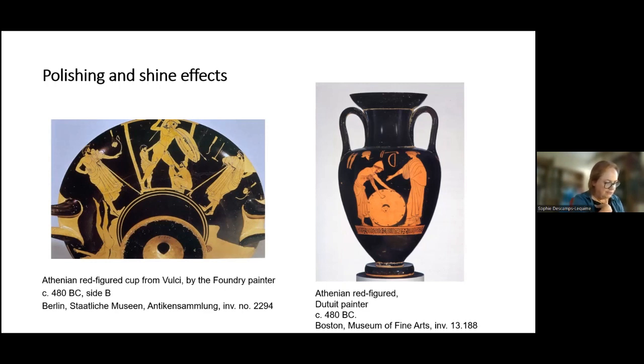Craftsmen completed the polishing process, as depicted on the foundry cup, by using a metal scraper. This tool, removing fine shavings, produced notches of varying depth, oriented according to the way it was guided. The scraper also vibrated to create small depressions perpendicular to the notches. These ripples were so dense that they generated significant light diffraction effects, accentuating the three-dimensionality of the works at locations chosen by the craftsman.